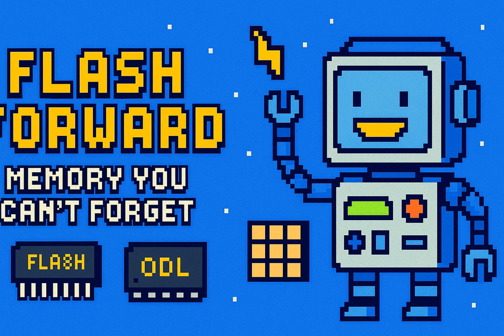So how do manufacturers ensure it still lasts reasonably long, endures enough cycles? Through extensive, rigorous reliability testing. A crucial test is data retention bake testing at high temperatures. Baking the chips. Essentially, yes. For plastic packages, maybe 150 degrees C. For hermetic, maybe 250 degrees C. High temps accelerate charge leakage. Simulating years of use quickly. Exactly. Allows estimating long-term retention under normal conditions.